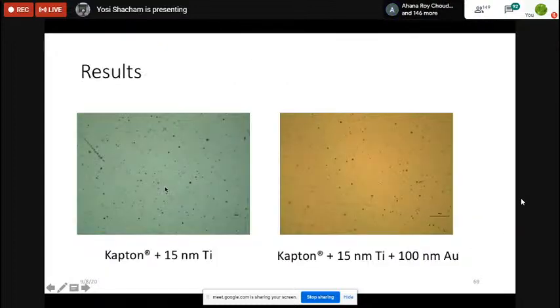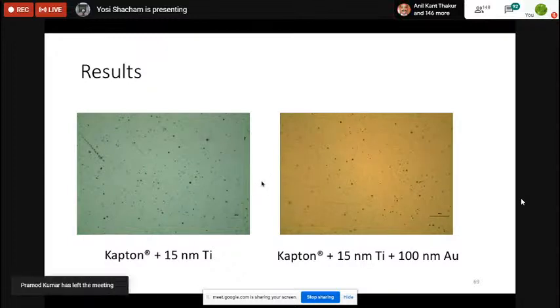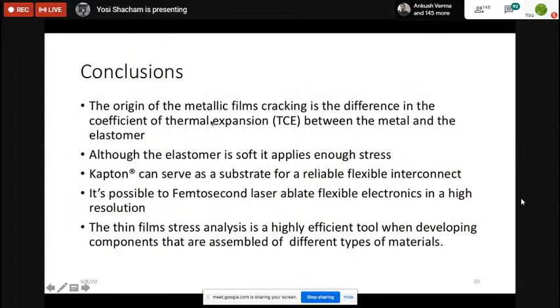So we developed a whole system, not only to make electrodes, but to analyze when they break and when they don't break. And we have a table: everybody that wants to use metal X on a polymer Y, we can predict beforehand if it's going to crack or not. So this is our contribution, that we can forecast for any combination of any metal, that we know the properties, if it's going to crack or not. So this is our conclusion.